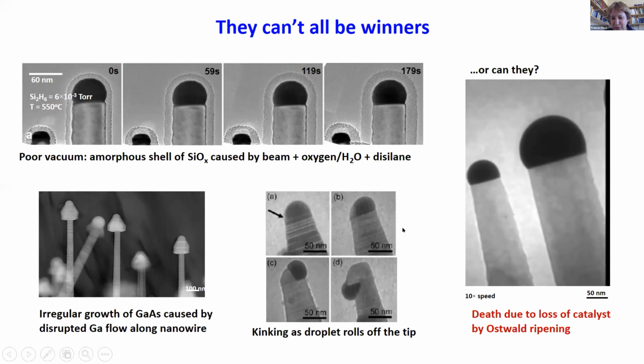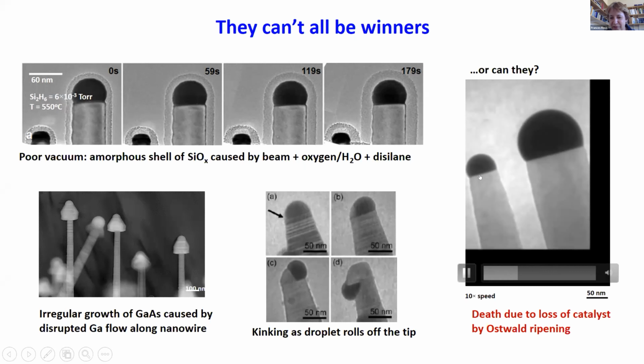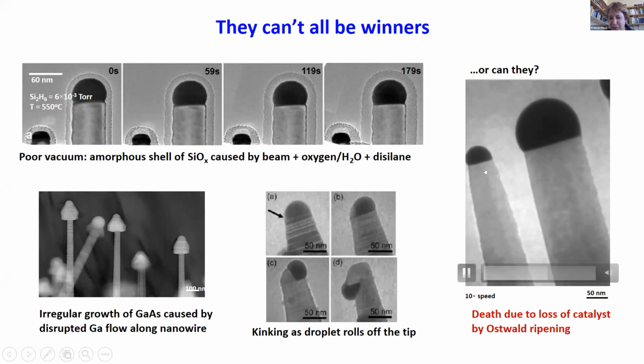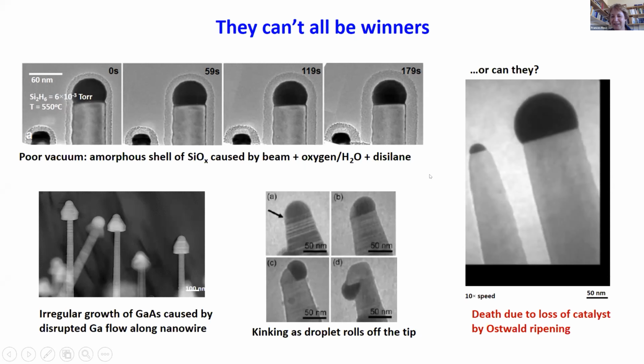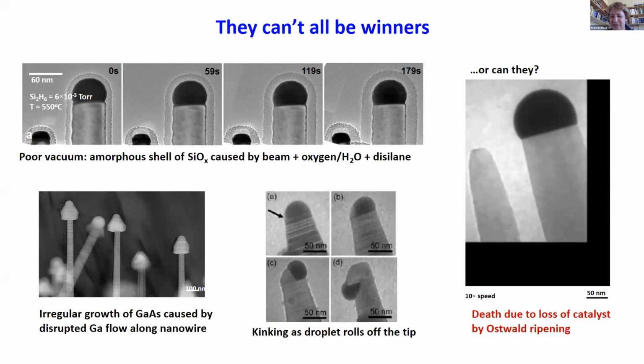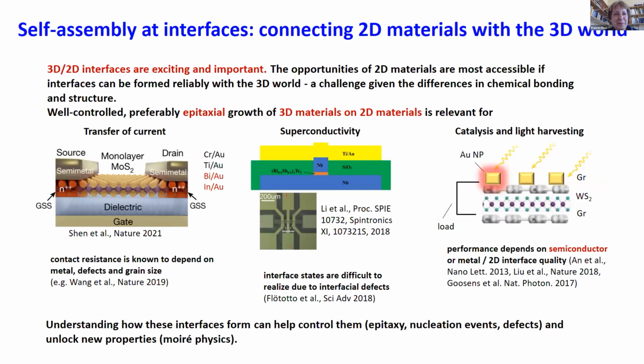And here's one of the most fun ones. We were very frustrated by this. Look, the small particles, they're growing. The nanowire is growing, but look, the catalyst is disappearing. And it took us a long while to realize that this is the same Ostwald ripening process I showed you earlier for germanium islands. The gold on the small droplet is diffusing down the nanowire, and it's going up and joining another larger droplet. So it provides a limit on the types of structures that you can grow. All right. So this type of work makes you think about other opportunities for controlling nanoscale structures that form spontaneously.